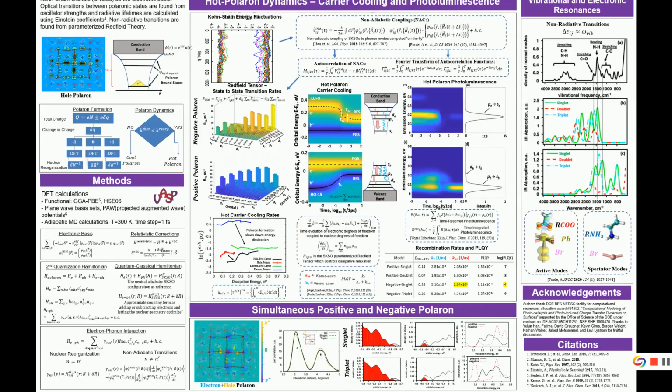So this describes non-radiative relaxation of excited polaron states. And then along the same trajectories, we can compute radiative relaxations. Essentially, we're trying to characterize the photoluminescence capability of the polaron, to see how efficient it could potentially be at emitting IR photons. These plots, same log time, give the energy of transition along the trajectory, and the colors represent intensity. Once the carrier cools, it gives photoluminescence from the post-cooling energy transition. And from this plot, we can see that the negative polaron has about an order of magnitude more intensity for emitting photoluminescence during its trajectory.